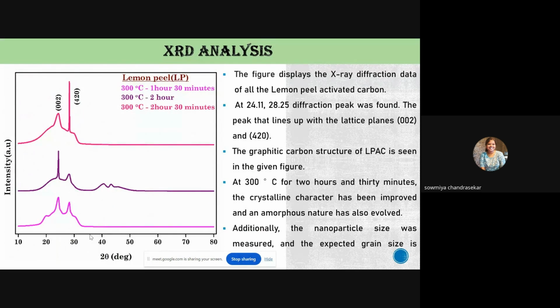The XRD analysis of 3 samples. In the figure itself, we can clearly see that LPAC carbonized at 300 degrees Celsius for 2 hours 30 minutes has 2 peaks at 24.11 and 28.25, which line up with the lattice planes at 002 and 420. The graphitic carbon is given in the figure. At 300 degrees Celsius for 2 hours 30 minutes, the crystalline character at 420 is improved, and the amorphous nature has also evolved.